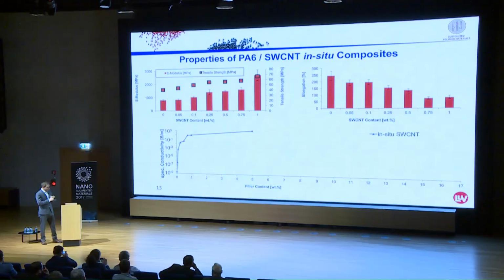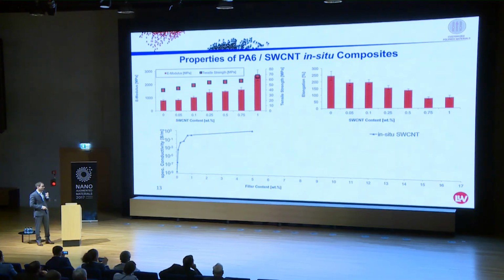And so it depends now on what you want to have. If you want a product with a good elongation and anti-static behavior, 0.1% of TUBALL is enough; we still have an outstanding elongation at break and anti-static behavior. If you want to go into the conductive area, you have to use maybe 0.7%, and you still have an elongation above 50, which is a great value here.